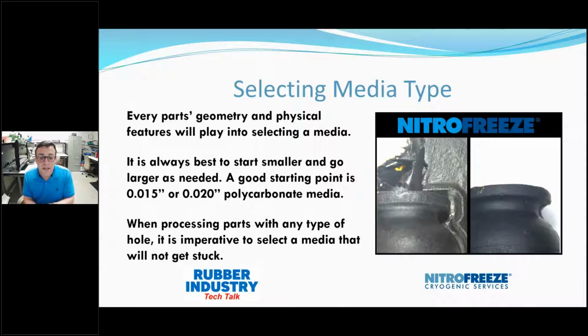So next, selecting the media type. I've got a part over here. This is an EPDM rubber part. It's got flash on it. It's got tear trim. The flash isn't very thick, but the tear trim is. On a part like this, this is where smaller media would come into play, especially with the edges of the part. It's got raised features, and we don't want to batter those down. So we would run, again, a smaller media. If we were to start that as a sample, we would process that with either a 15 or a 20 thousandths media.